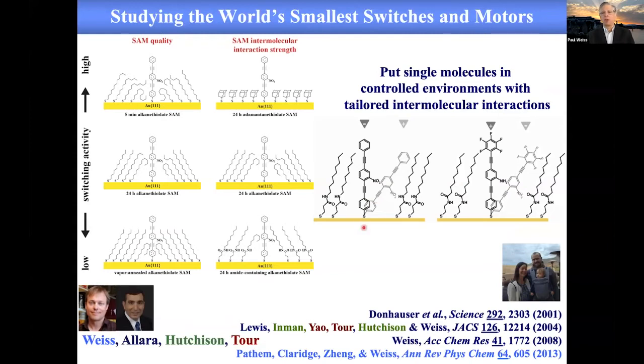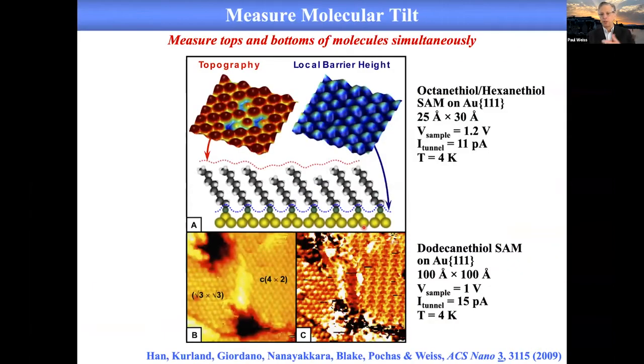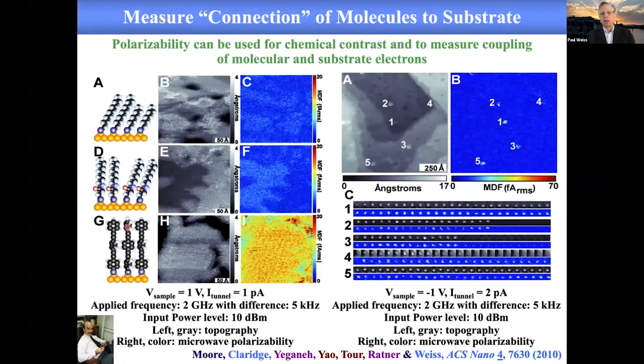We developed tools to look underneath the surface so we could see where this buried bond was and thus measure the tilt. This is another cousin of the scanning tunneling microscope, and these measurements can be done simultaneously. We can measure the polarizability of the molecule, which, when the buried contact is conducting, includes the electrons of the substrate. And this was done with Terry's colleague, Mark Ratner, who celebrated a birthday earlier this week.